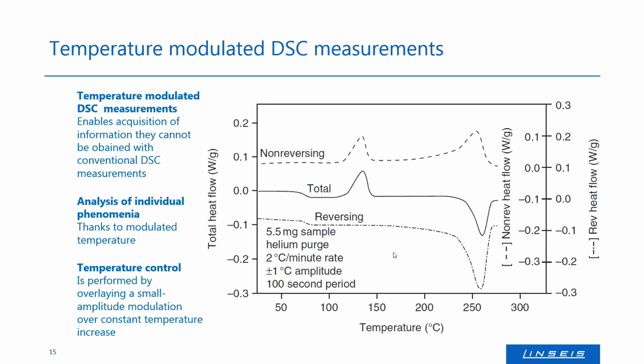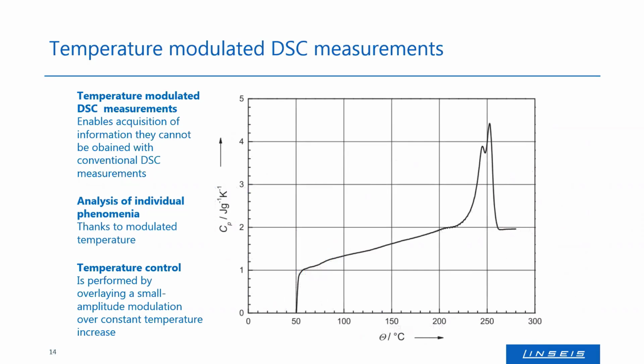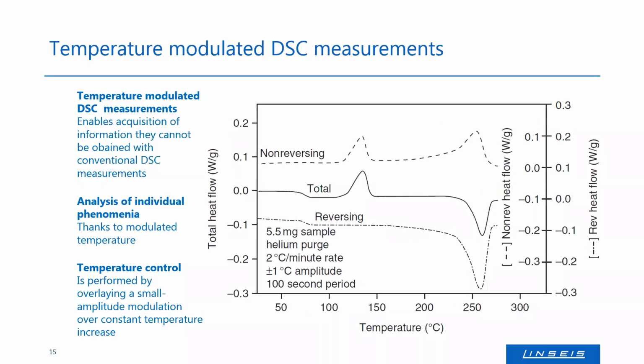If you remember on the last slide, it looks almost like the reversing heat flow. Let me go back. Okay, this is the reversing heat flow flipped upside down, and that's totally right. So the reversing heat flow is the reverse of our CP signal. So also here we can see our glass transition and the melt. And what does this say? Okay, the glass transition and the melting is a reversing transition here. So it doesn't matter if you heat it up twice, 3 times, whatever, you will always see this glass transition and the melt here.